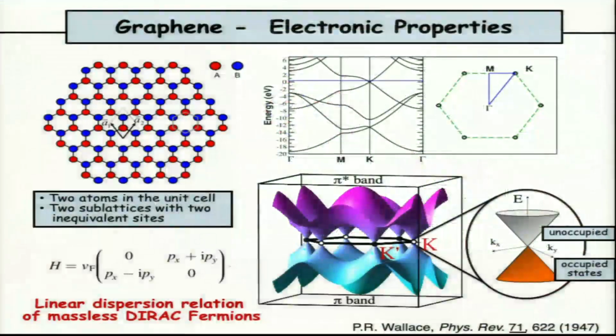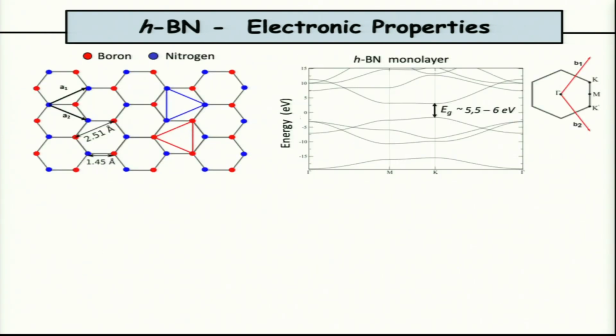So boron nitride is exactly the same as graphene, except that, well, I forgot to mention that in graphene you have two sites in the unit cell. You have two carbon atoms, but you have one which is blue and one which is red, because in fact they are not on the same triangular lattice, as you can see here. So you have these three red and you have these three blue. So you have a new quantum number that can be associated to the wave function, which is called the pseudospin. And this pseudospin is quite important to, in fact, investigate theoretically the electronic properties of graphene.